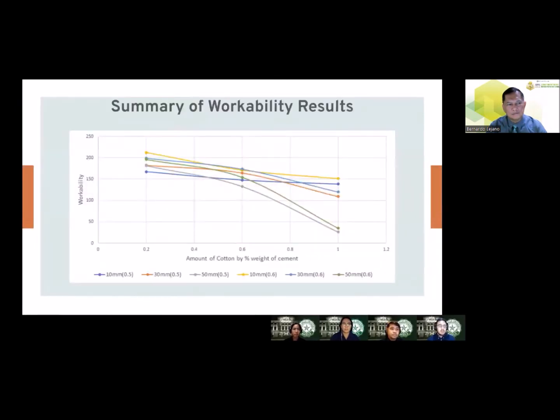Now, based on the results, it can be observed that the higher water to cement ratio yields a higher workability, and that the increase in the ratio of water in the mix resulted in an increase in the workability. It can also be observed that the workability decreases as more cotton is added into the mix, and there is a steeper decline in workability for longer cotton fibers as more cotton is added.